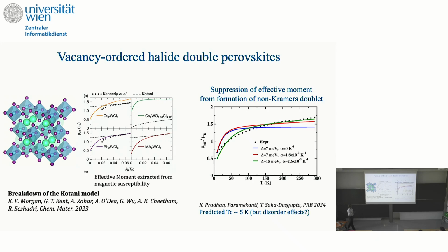And what we found is, in fact, even this behavior of the magnetic susceptibility, one can understand because, remember, if you have this 5-fold multiplet with J equal to 2, the magnetic moment is significant. But if it splits into a lower doublet that's non-magnetic and a magnetic triplet that's excited and off in energy by 100 or 200 Kelvin, then as you cool the system, the magnetic moment will vanish because there is no dipole moment in the ground state. And so if you do this, with some modest assumption about the scale of the gap, you can more or less reproduce, with this green line, the data